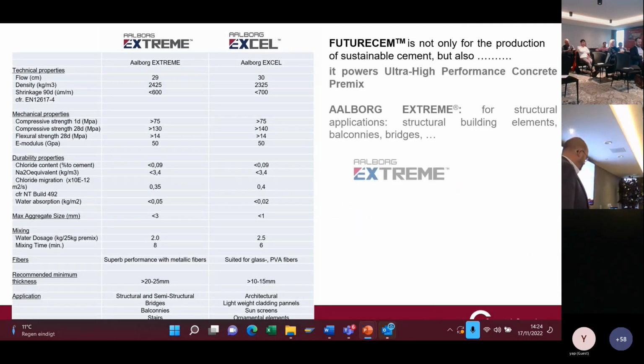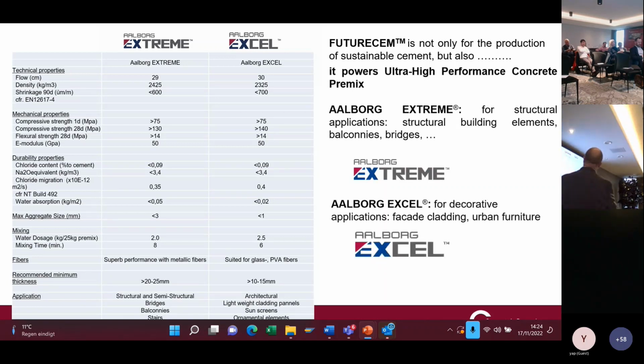So the first product we put into the market was the Aalborg Extreme, but we made a second version of it because we wanted, also for decorative applications, a matrix that is even finer than the one for Aalborg Extreme. So there is a difference you can see in the aggregate size. For Aalborg Extreme, we have the T-max of 3, and for the Aalborg Excel only maximum 1 millimeter. And also the flow is a bit better, let's say, for Aalborg Excel. It makes it possible to have complex formworks.